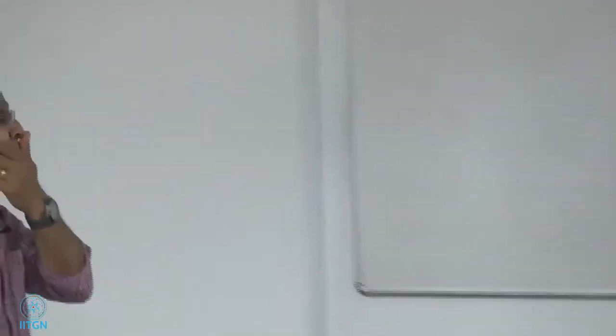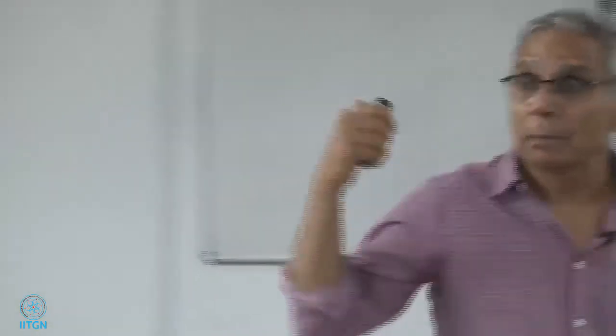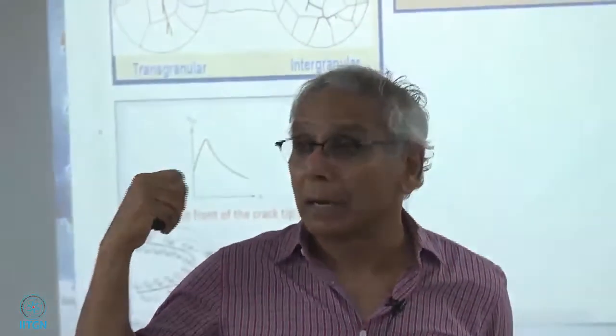It's interesting that this pit, even though it's larger than this, doesn't have a crack. It's kind of funny. So a lot of times what you can do, you can take this as a tensile sample and do your high cycle fatigue life to see what is the fatigue life in the presence of pits. Because the corrosion pits affect the high cycle fatigue because of those kind of cracks coming out from the pits.